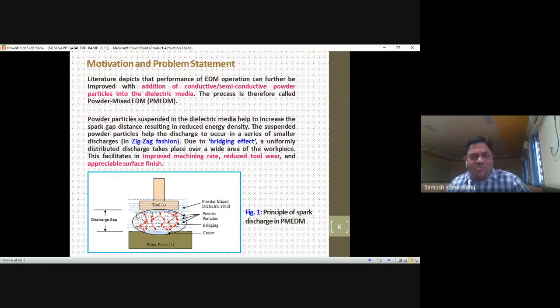So due to the bridging effect, a uniformly distributed discharge takes place over a wide area of the workpiece, and this facilitates improved machining rate, reduced tool wear, and appreciable surface finish. These are the limitations in our traditional, normal EDM. That's why we eliminate them to some extent by adding powder into the dielectric.